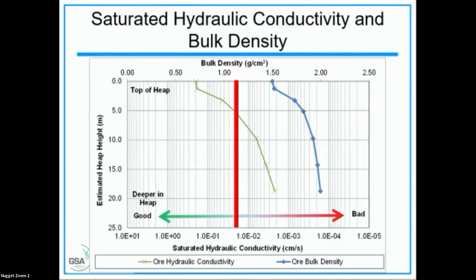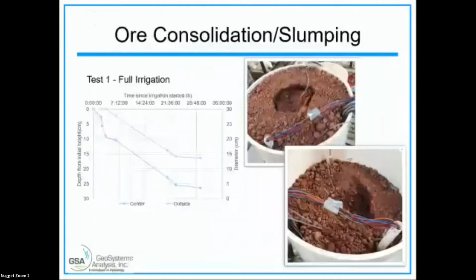This is the bulk density curve on the second x-axis up here. You can see it starts off with a very light bulk density, and then it ramps up very quickly by the time we get to 5 meters. And this is 5 meters in the heap. So you've got all this overburden pressure. By the time we get down to 5 meters, we're around 1.8. That's usually a bulk density beyond which you might start having problems. By the time you're at 10, you're almost at 2 grams per cubic centimeter. Very high bulk density, you're definitely going to have problems. Next slide.